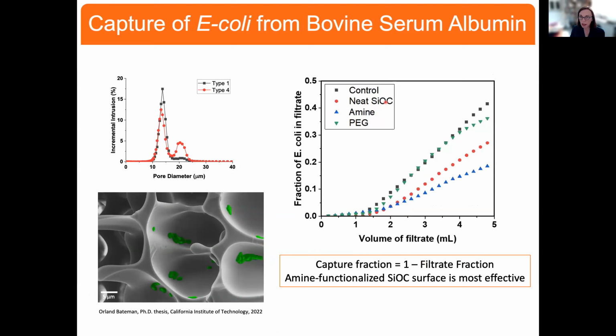We can do this as a function of just the neat SiOC, which here the capture fraction is 1 minus this value of the fraction of the E. coli that we actually pick up. And we find that basically, if we have a functionalized surface on these porous materials, we can capture a very large fraction, about 85% of the E. coli. So it's most effective at doing that.